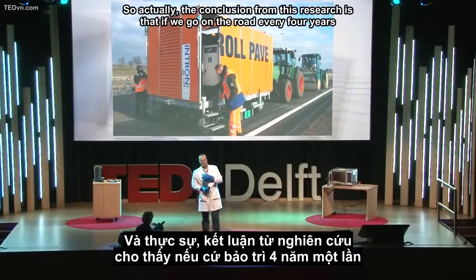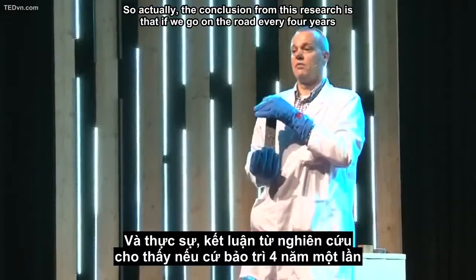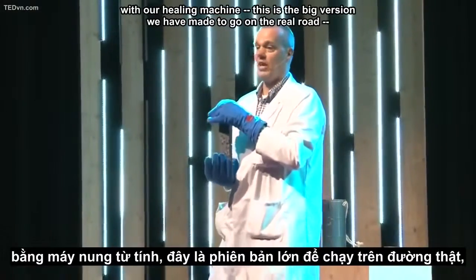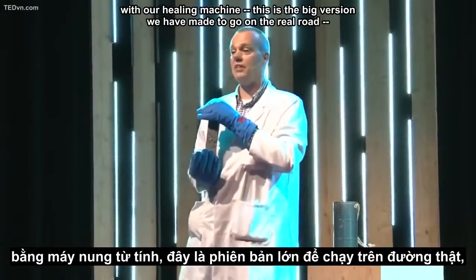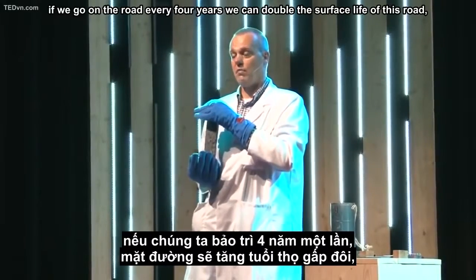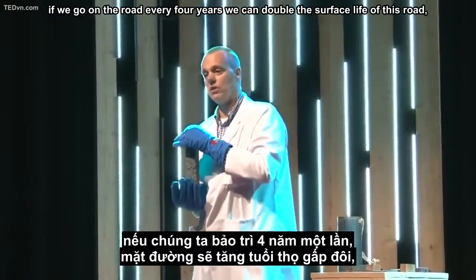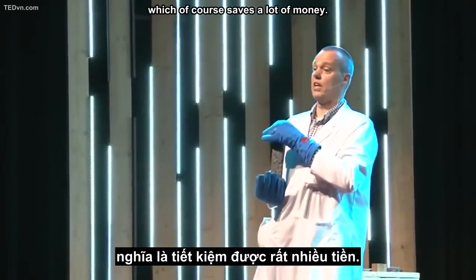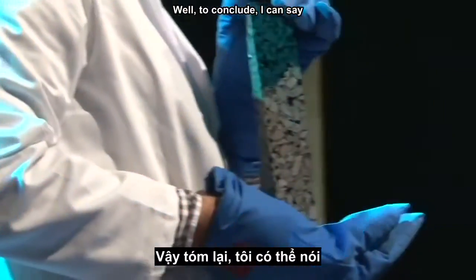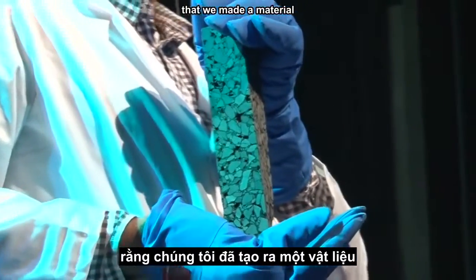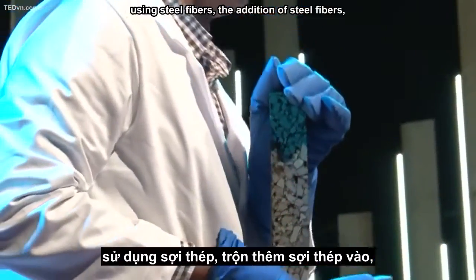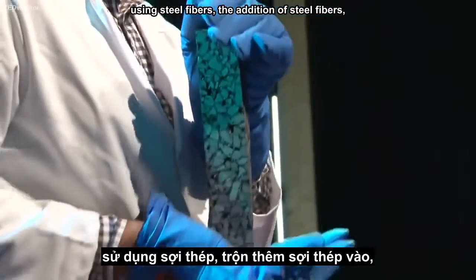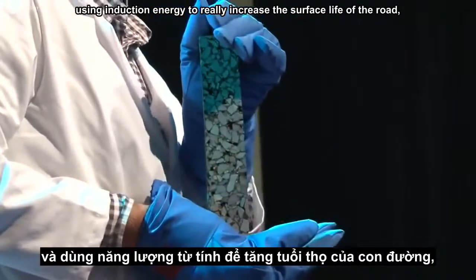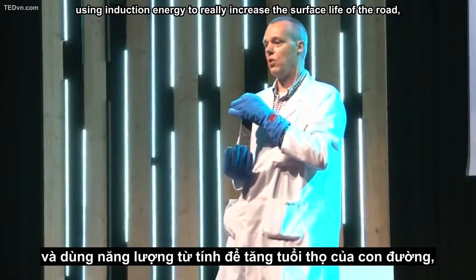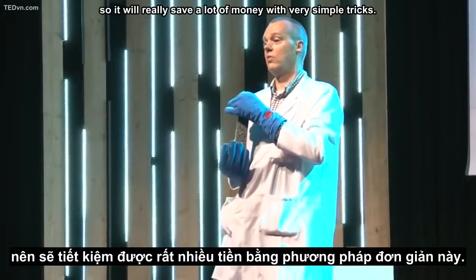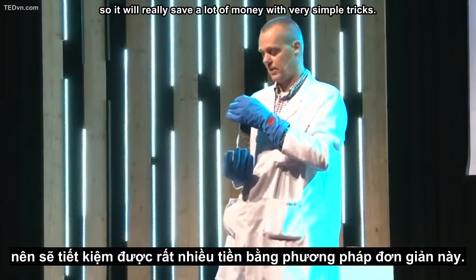So actually the conclusion from this research is that if we go on the road every 4 years with our healing machine, this is the big version we have made to go on the real road, we can double the service life of this road, which of course saves a lot of money. Well, to conclude, I can say that we made a material using the addition of steel fibers, using induction energy to really increase the service life of the road, even double it, so it will really save a lot of money with very simple tricks.